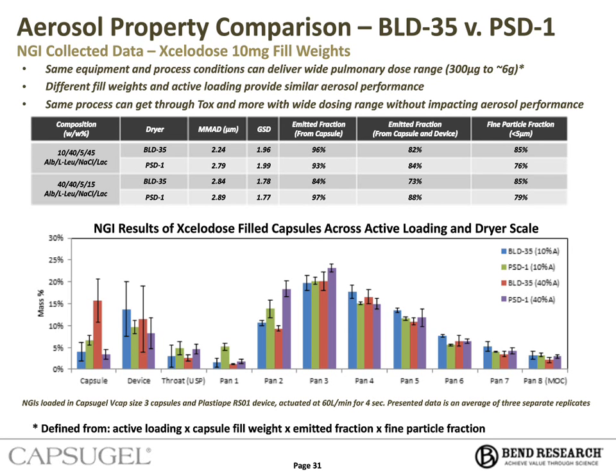And so basically what's shown within the different fine particle fractions, emitted fractions, and active loadings and fill weights is a dose range of 300 micrograms to 6 grams that can be achieved from a single capsule. So this is pretty important that the same process can get through tox and more with a very wide dosing range, with the key that it does not impact the aerosol performance.